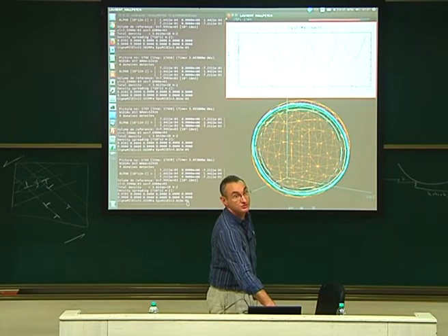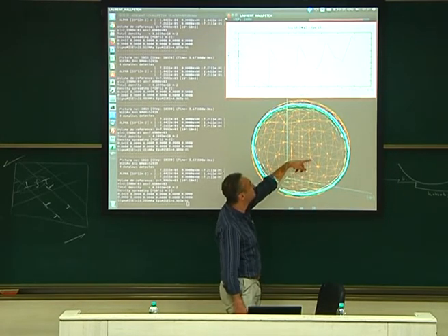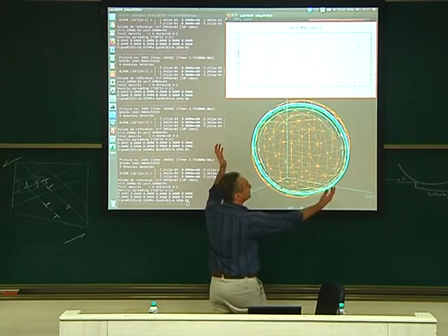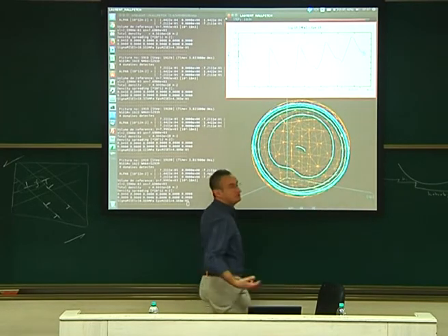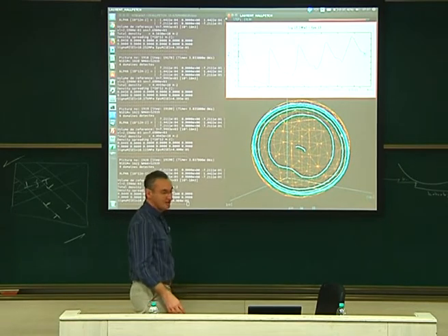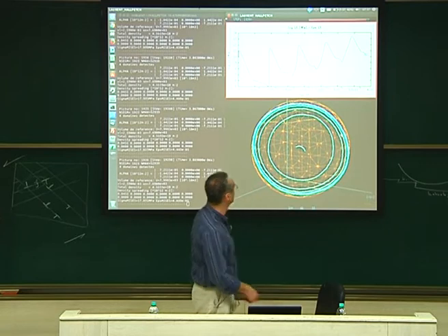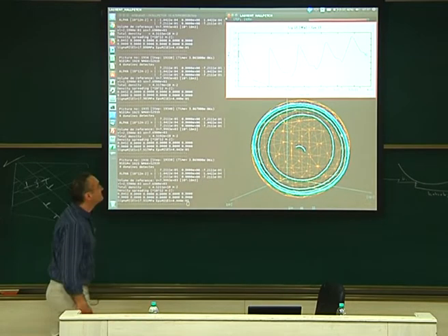So this is because of the back stress. The back stress needed to move the dislocation is bigger and bigger with time because you have those back stresses which are impinging the motion. So this is typically the back stress. So this is the kinematic hardening, you see. So here you have the loops coming out and so on and so on. Okay? So this is for that.